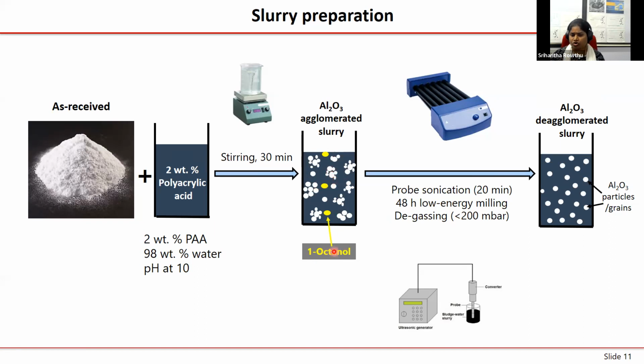If you don't do that, and you cast it ultimately, then you are going to end up having very big, unintentional or undesirable voids in your material. We don't want that. So you have to break down all the air bubbles present in the slurry. This agglomerated slurry is not good to cast, so you have to further do a de-agglomeration process. For that, we have employed 3 steps. The first is probe sonication, using this probe sonicator, for around 20 minutes or so.